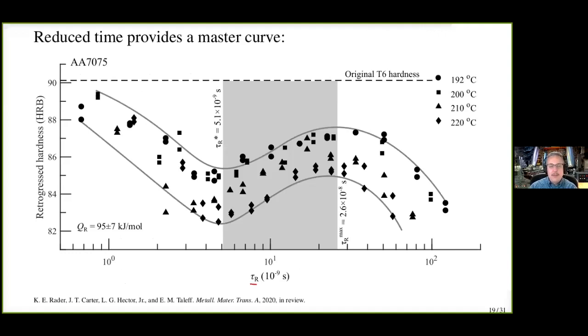So here we have the retrogression time as a reduced time. So we're using that activation energy to multiply retrogression time by exponential Q over RT. And then we're plotting the hardness here, which is uncompensated. What's happened is all the data at these 4 temperatures are all shifted so that the minimum here at our TR star occurs at the same time, and the maximum here at TR max occurs at the same time if we're using reduced time. So we now know that we have a predictive way to alter temperature and predict how much our time is going to change for this retrogression.